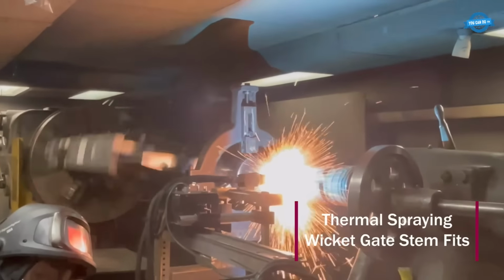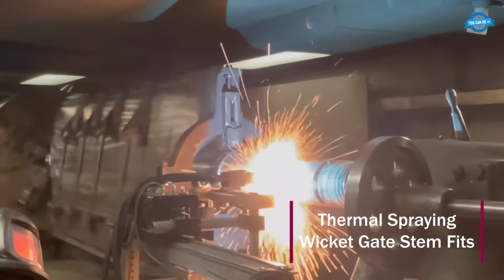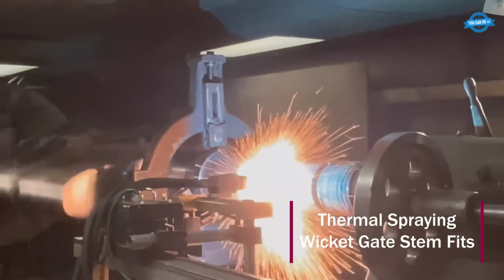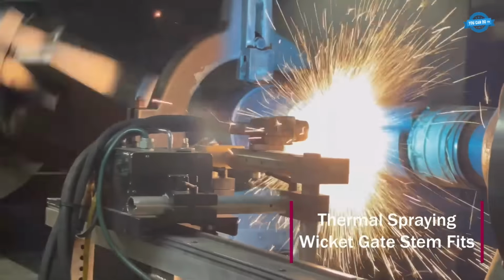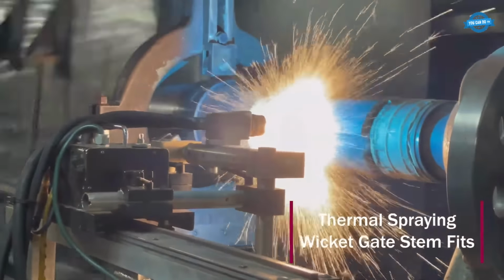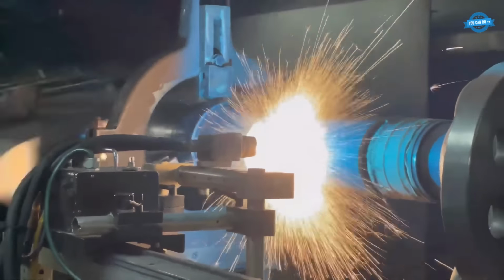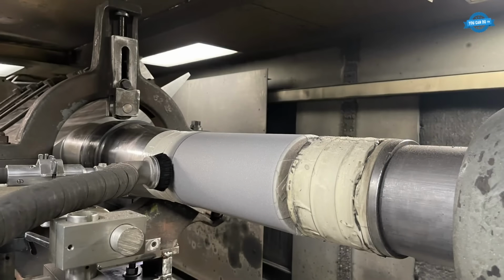Hydroelectric wicket gates get restored through thermal spray. A 420 stainless steel coating gets sprayed onto worn journal fits at bond strengths up to 10,000 pounds per square inch, restoring the surfaces to original factory specifications.